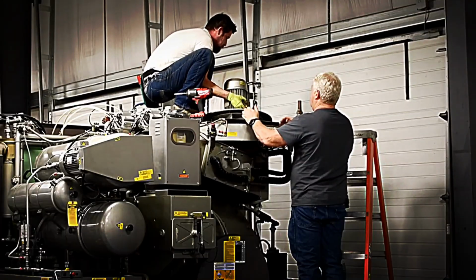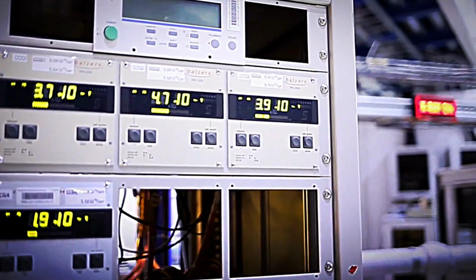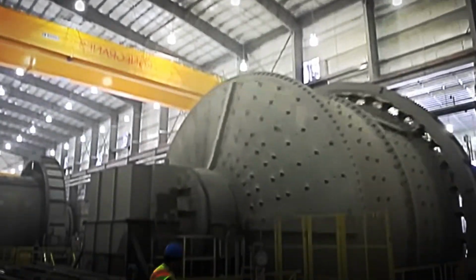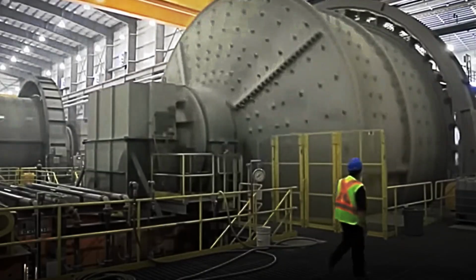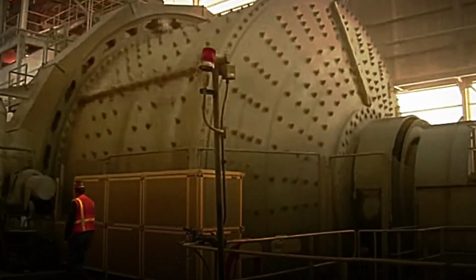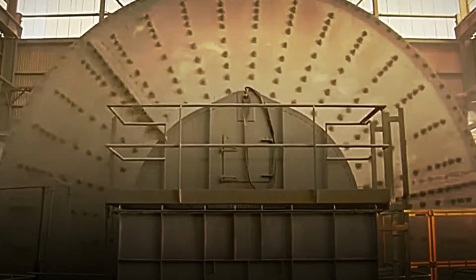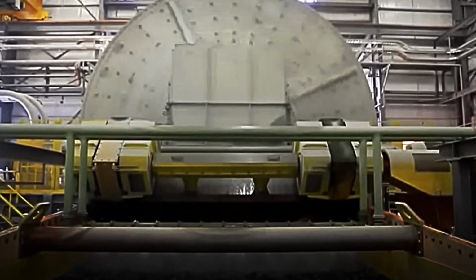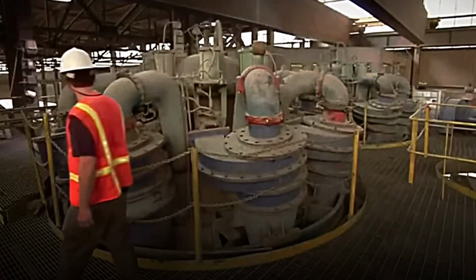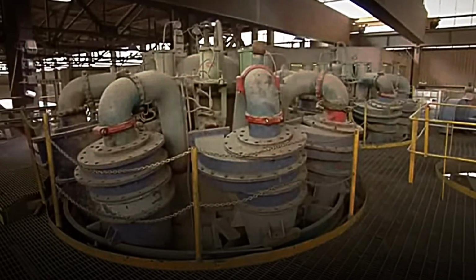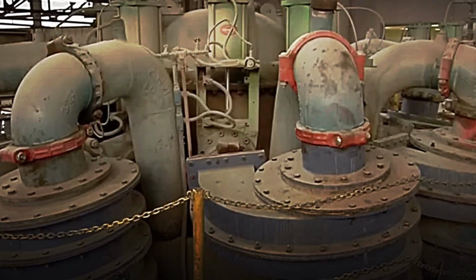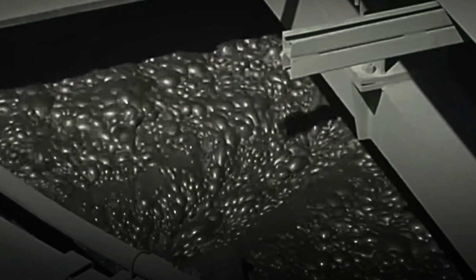It first passes through a rotating mill where steel balls crush the rock into tiny particles. From there, the material passes through a secondary grinding circuit until it is reduced to powder. Chemical reagents and a foaming agent are then added. The mixture is introduced into flotation cells, where air bubbles drag the copper particles to the surface. This metal-laden foam is collected and filtered, obtaining a concentrate with a purity of 25 to 30%. The concentrate travels by train to the smelting plant.